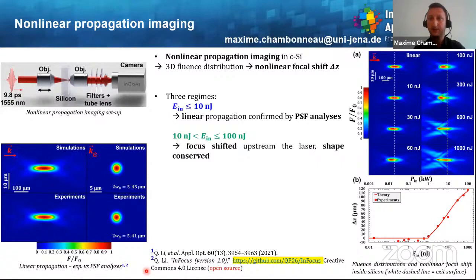Then for intermediate input pulse energies, so back to those data here on the right, between 10 and 100 nanojoules, one can see that the focus becomes unambiguously shifted upstream of the laser. However, the overall shape, I would say, is conserved. And then the final regime is when you increase the energy a lot and go to more than 300 nanojoules. And then one can see that we are in the filamentation regime, especially here for 1 microjoule, where you see those focusing and defocusing dynamics.